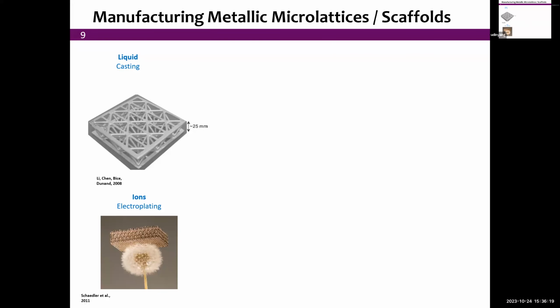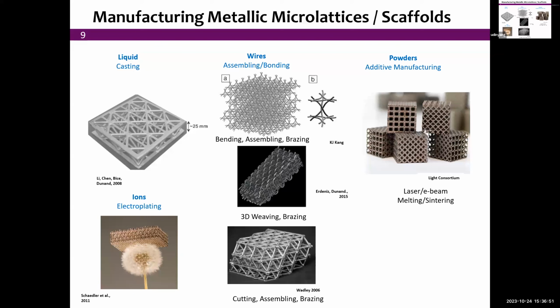So I will be talking about specifically micro-lattices, often called scaffolds. And I don't think I need to introduce why we're going to do this. It's really to get high strength, high stiffness, low density, lightweight materials that are metallic. But I want to talk about the many ways that people have made those materials. We can cast, essentially lost wax casting. This tends to be rather large, roughly 1 inch, or you can make them by electroplating, which is extremely lightweight and much finer. You can use wires that can be assembled, bonded, brazed, etc., into those,